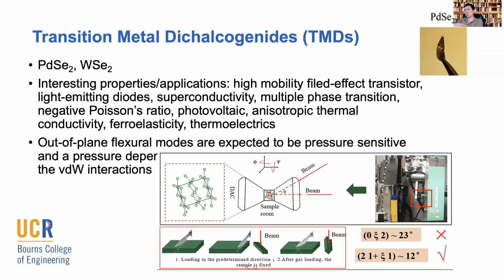What we usually need to do is load those samples inside the diamond anvil cell and apply pressure, and we do inelastic X-ray scattering. For inelastic scattering, we are very much limited to working along the axis of the diamond anvil cell. That poses a big constraint on what region of the Brillouin zone we can explore, depending on how the samples are oriented inside this diamond anvil cell.